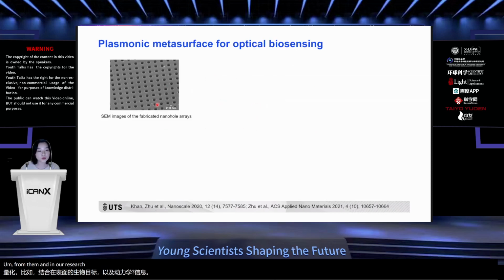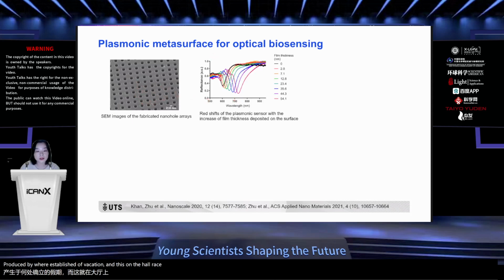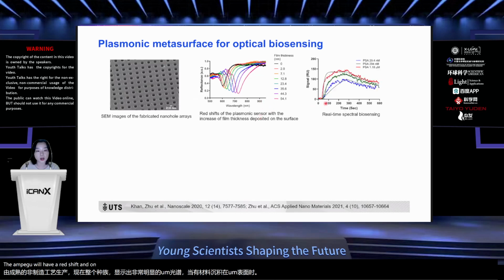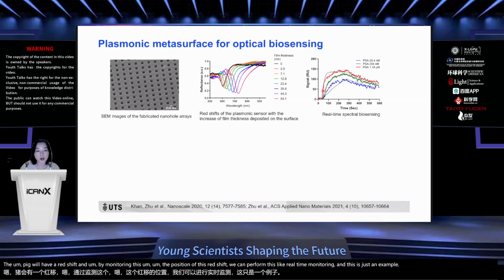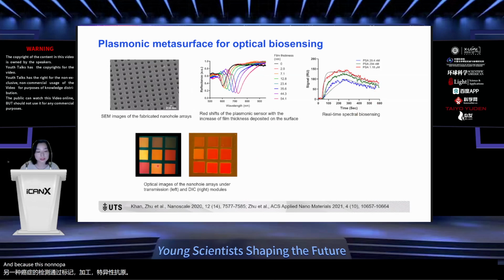In our research, instead of using the gold film used for standard surface plasmon resonance, we fabricate plasmonic nanostructures. For example, we can fabricate these nanohole arrays produced by well-established nanofabrication. These nanohole arrays show a very distinct optical spectrum, and when there is material deposited on the surface, the peak will have a red shift. By monitoring the position of this red shift, we can perform real-time monitoring. This shows an example of the detection of another cancer biomarker, prostate-specific antigen. And because these nanoplasmonic chips have unique colors, we are also working towards using the color change for sensing purposes.